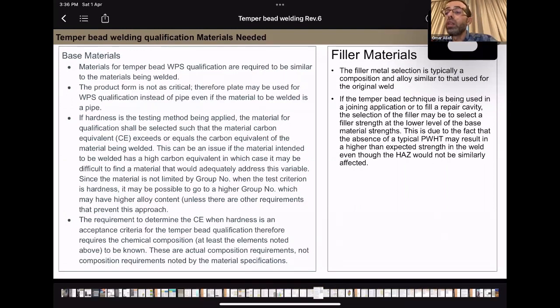The filler wire typically should be the same composition as the original weld, but sometimes in some studies it is claimed that using a filler wire with lower strength is preferred. This is due to the fact that the absence of typical PWHT might result in higher than expected strength.